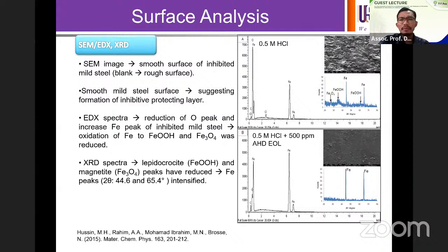So some other advanced techniques that we did were surface analyses. Without the presence of the modified lignin inhibitor, you can see that the surface of the metal is very much corroded after being exposed in acidic medium. And the XRD spectrogram also shows the presence of different rust phases, oxyhydroxides and metal oxides. But as we introduce the modified lignin, you will see that the surface of the metal is very much smooth. And from the XRD, we don't see much presence of other types of rust phase. Even from the EDX, you can see that the oxygen content is very much reduced as compared to without the presence of modified lignin inhibitor.